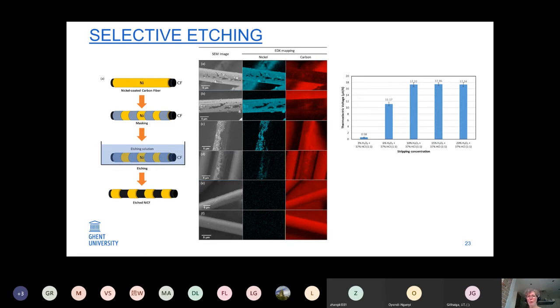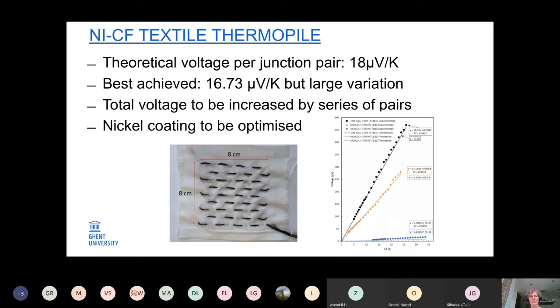And you can see that from a concentration of 10% peroxide, the nickel layer is fully removed, or at least it is removed up to an extent whereby you have an optimal functioning of the system. Then integration in a textile. Here the yarn has been inserted by hand because the etching has been done at the level of the fabric, and we achieved a thermal voltage of 16.7 microvolt compared to a theoretical maximum of 18, which is an efficiency of more than 90%, which is quite good.